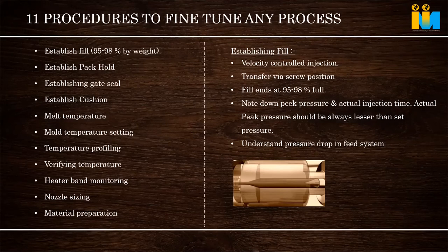That is the third point, gate sealing time. What time does the gate seal? How is it done? Suppose I fill the part 90 to 95% in injection, and only some sink marks are there. Now I give a holding time of 1 second at 50-60 MPa pressure. A slight amount of sink mark is reduced. Again, I change it to 2 seconds, and the sink mark reduces again. I measure the part weight and it has increased.